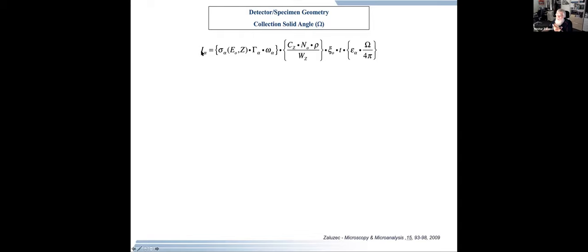And that spectroscopic intensity, I alpha, is proportional to some physical parameters due to the electron-solid interaction and what signal we're measuring. In this case, the cross-section for the ionization of the material, any radiative partition functions and distribution functions, the number of atoms in the material and the volume we're analyzing, the beam current, the analysis time, and our collection efficiencies. Now, rather than talking about EDS and EELS, I'm going to focus for the rest of our discussion today on EDS, because that's where some of the latest and newest advances have come in. We really define our experiment by the parameters of the instrument, which affect the physical processes that go on, the cross-section and fluorescence yields. The number of atoms we're not going to change, that's the volume of material. The beam current and time we can analyze. But of all of these, the things that we can improve on without destroying the sample is really our collection efficiencies.